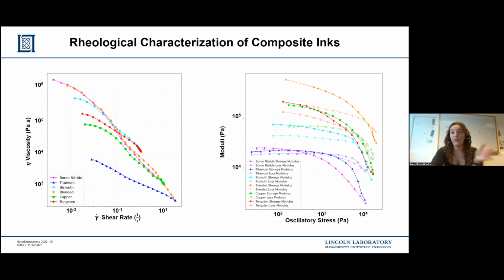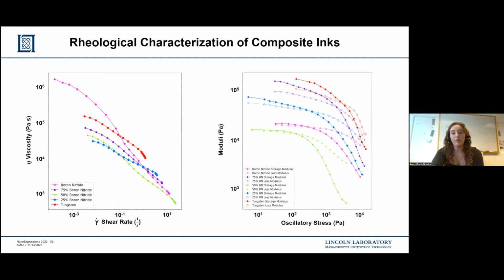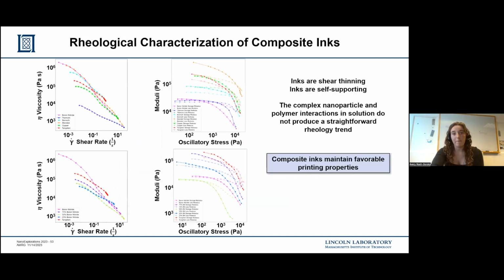We did this both for the inks that I showed using one element on the periodic table and also for our graded shields, which have the same behavior, obviously, because we needed to be able to print them. So the key takeaways are that our inks are shear thinning, our inks are self-supporting. Unfortunately, the complex nanoparticle polymer interactions prevent any straightforward rheology trend from being seen, but it doesn't fully matter because it has those two key features of shear thinning and self-supporting.